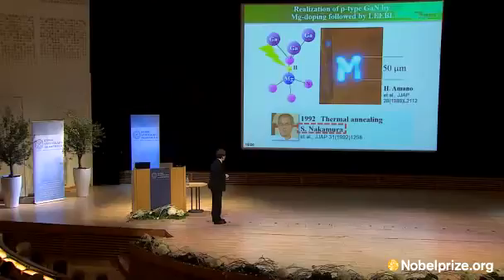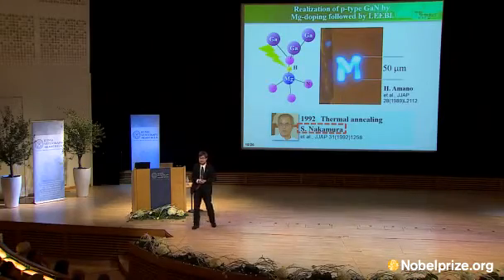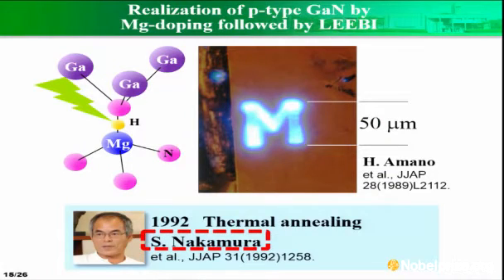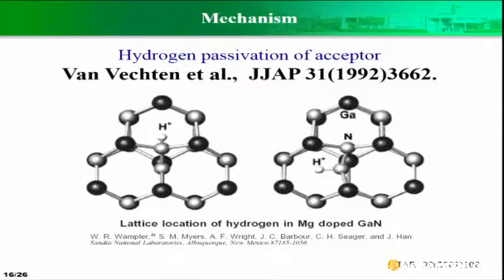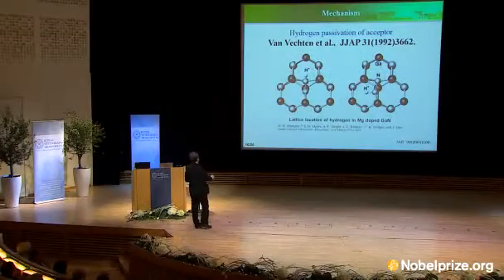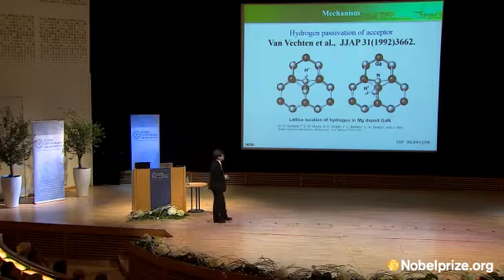In 1992, Professor Nakamura claimed that he could realize p-type gallium nitride even by a much simpler method, that is, thermal annealing. The mechanism is shown here. In the as-grown sample, the magnesium was passivated by hydrogen. So the LEEBI treatment or the thermal annealing is effective to dissociate the hydrogen from the passivated magnesium, which was first explained by Professor Van Vechten in 1992.